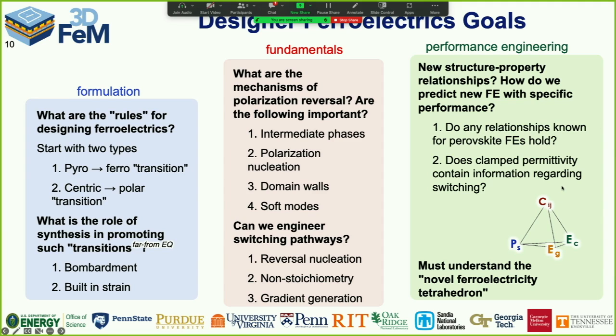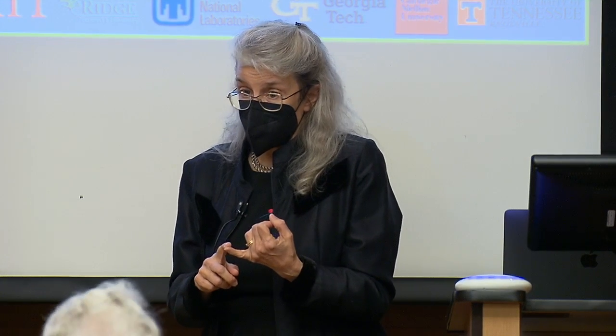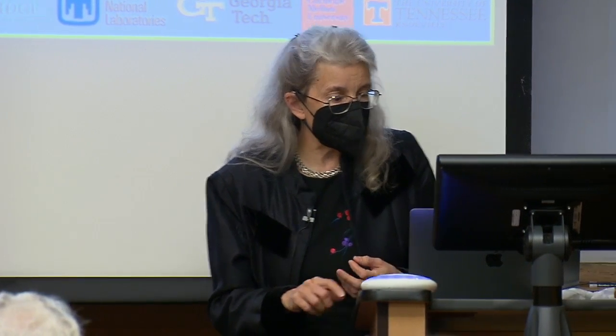And we speculate that there's actually going to be a performance tetrahedron that's going to say, I'm going to design the best materials based on how big's the polarization, how big is this elastic stiffness. The stiffer it is, the harder it is to reconfigure bonds in the solid. How big's the band gap? If I have to blow the material up to switch it, that's probably not going to be appealing. And yeah, I think we've got all of them there, and the coercive field.